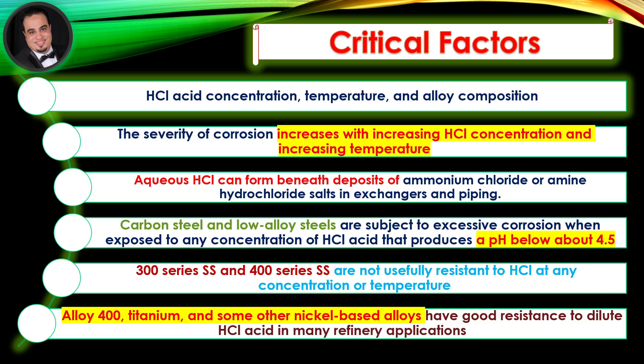Aqueous hydrochloric acid can form beneath deposits of ammonium chloride or amine hydrochloride salts in exchangers and piping. Carbon steel and low alloy steels are subject to excessive corrosion when exposed to any concentration of hydrochloric acid that produces a pH below about 4.5.